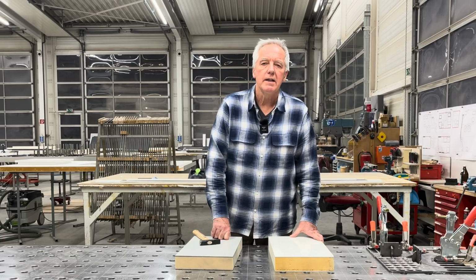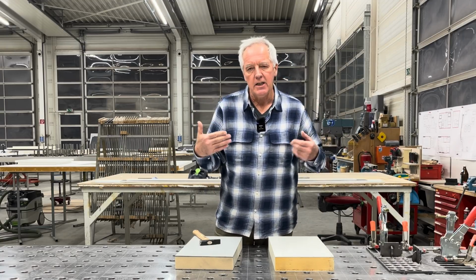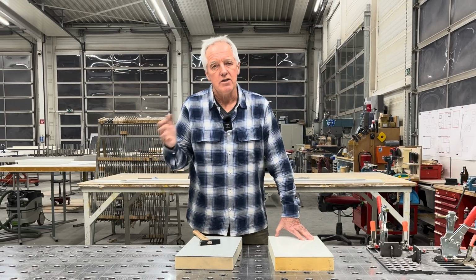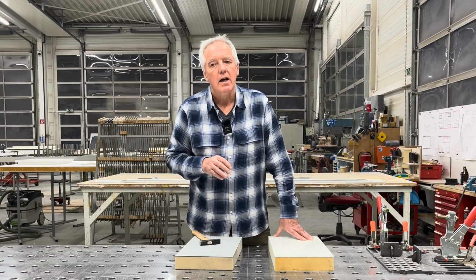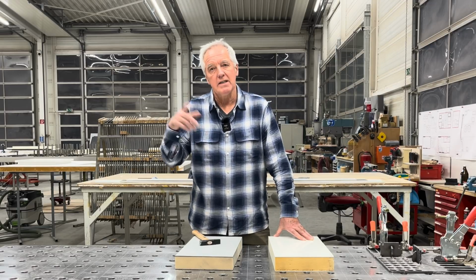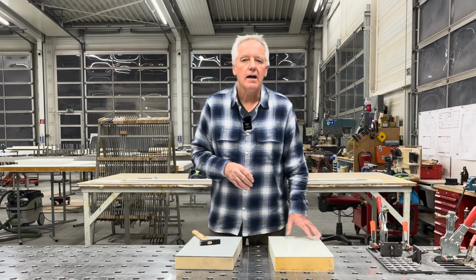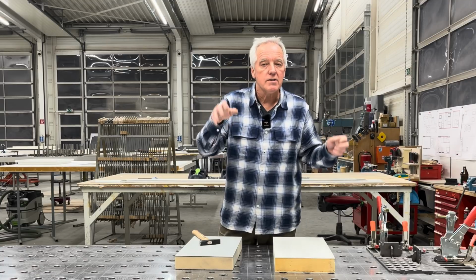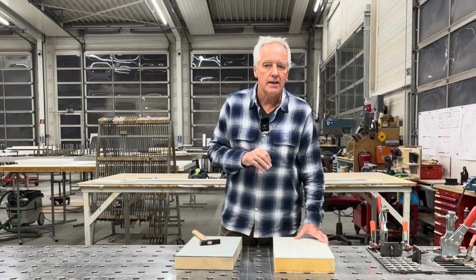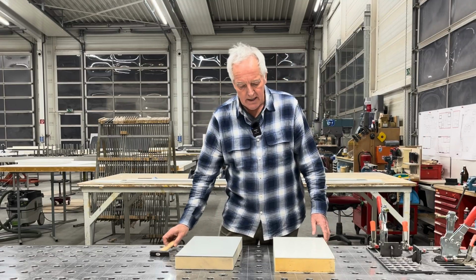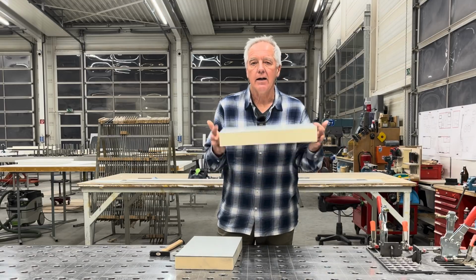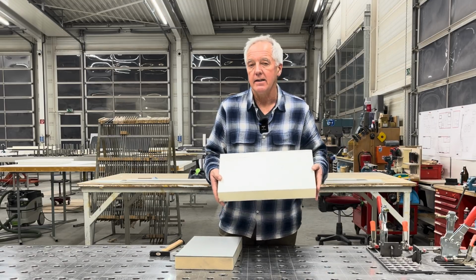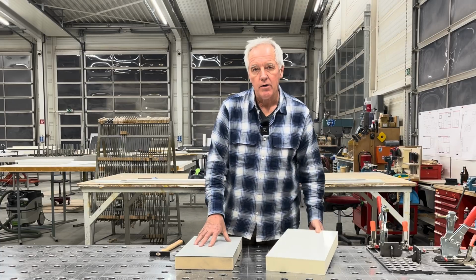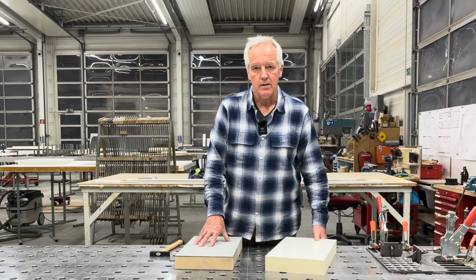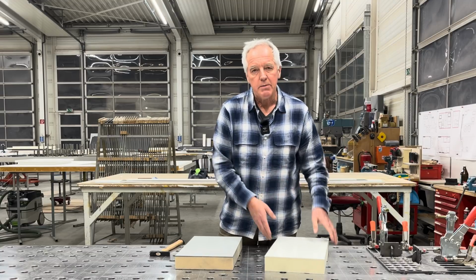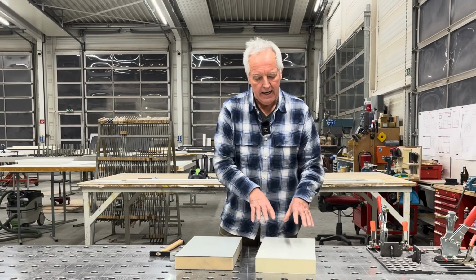So for example, when you build a body with a steel frame and sheet metal, you should expect like 22 kilos per square meter. If you do it in aluminium, which is 3 times lighter, but you need more material, you go down to almost half of it, let's say like 11–12 kilogram per square meter, while a square meter of this fiberglass panel is 11 kilo, and this carbon panel is about 7 kilo. So you see that there isn't a big weight difference between an aluminium body and a fiberglass body.